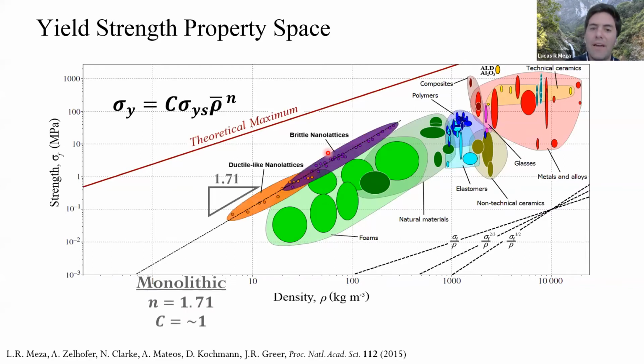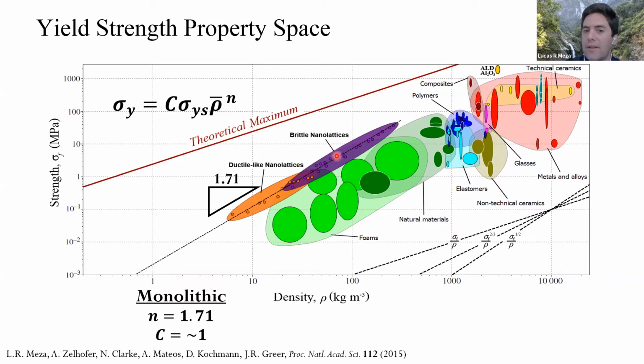And from that, here now we can see this is where our monolithic lattices fell. So you can see if I drew a line up to that, this line would effectively intersect my ALD alumina. So we're getting higher strength, or higher stiffness, at the same density than normal foams. That's primarily driven because we're using a stronger constituent material.